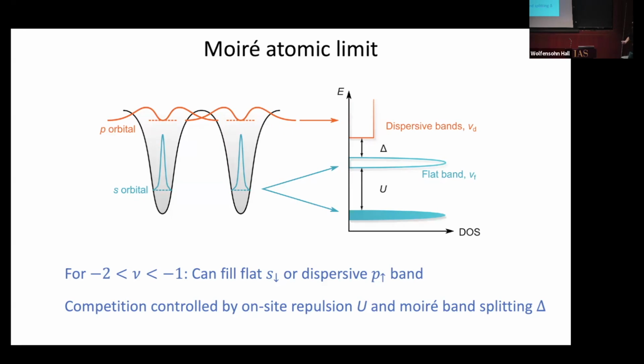Doping up to 1 hole per Moire unit cell, it's obvious you're going to fill one of these s orbitals. Then between 1 and 2, you have a choice now. There's some on-site repulsion that plays a role, and so there's some effective Hubbard U that opens up a band gap between this occupied s orbital and the next s orbital, which, at least in a magnetic field, must have opposite spin from the occupied band. That's one option, whereas you also have these more dispersive bands that come from the p orbitals. They're more dispersive because the p orbitals have a larger overlap.